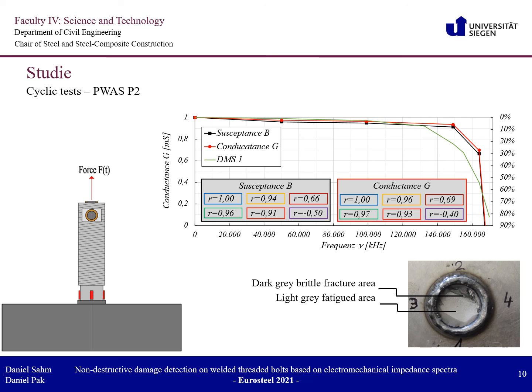After 130,000 load cycles, the strain and the correlation of the spectra are at about 93.5% of the original level. After a further 16,500 load cycles, the strain dropped by 22%, while the correlation coefficient of the conductance and the susceptance spectra has a value of 91%. From 149,000 load cycles, the correlation of the susceptance and conductance spectra also drops significantly. After 164,000 load cycles, the correlation is only 66% and 69% respectively.